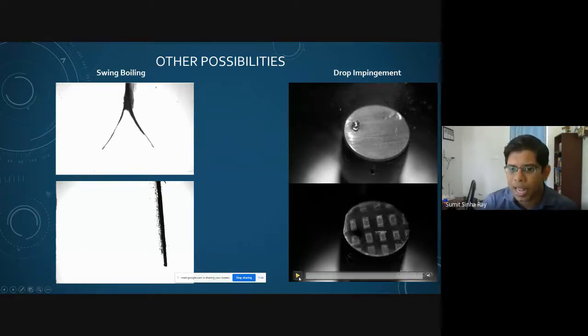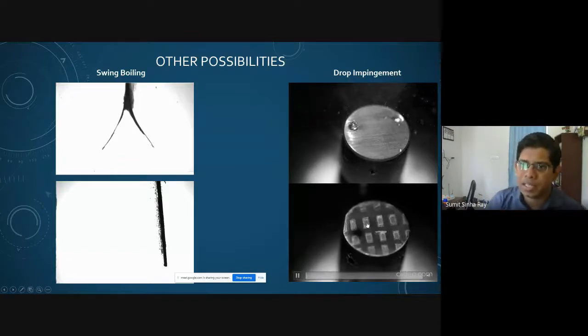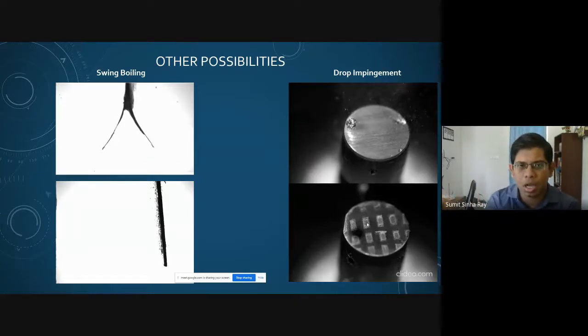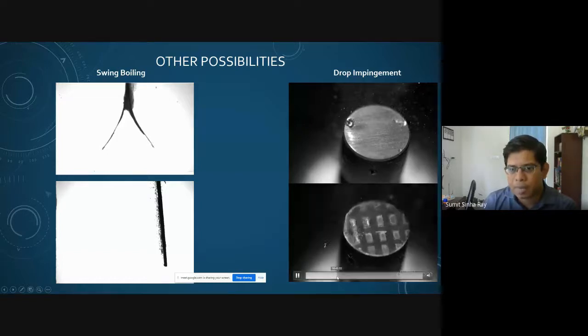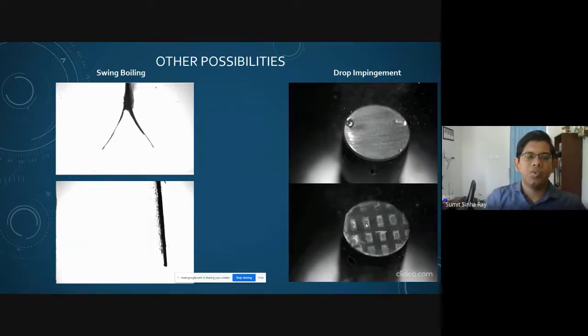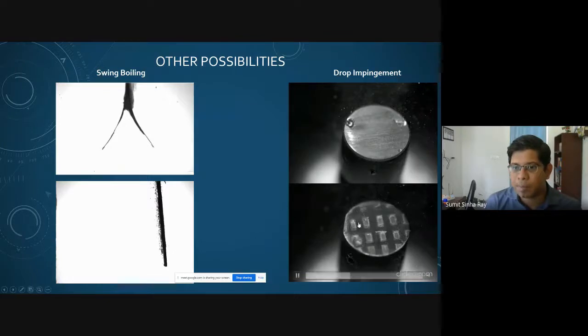On the other hand, if we have a textured sample like this, where we mimic all these cold and hot spots, and we put this texturing on it, and I'll just skip a little bit, you see that these droplets over here, where earlier these droplets have left, got pinned, and they cannot leave the surface anymore. Thereby, we use the entire potential of these nanotexturing in terms of heat removal. So these portions have been boiled, and this droplet cannot leave the surface anymore.